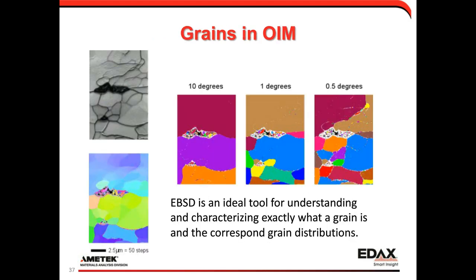I mentioned earlier that we define a grain tolerance angle, and EBSD is a great tool for looking at grains under different grain tolerance angles. There's a great question of what number defines a grain. I don't know if there's a great answer, but EBSD and OIM are great tools for looking at that. This is a really nice example. The image on the top left shows an image quality map, which reminds me of a TEM type image where we see a lot of grain boundary contrast in the material. The image on the bottom left shows an orientation map, so here the colors are showing orientations. We see that this material seems to have what I'd almost call a subcell type structure. When we create the grains, we randomly color the grains.